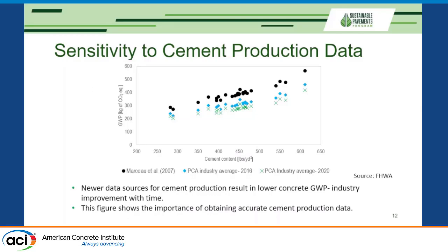I have shown you strong linear correlation between cement content and GWP. And it is true because cement is the most significant component. It has the highest contribution to footprint of concrete. But there is one more thing happening here. My LCA is following that prescribed in EPD program, so we are using only one inventory for cement. We are using industry average cement from 2020, which is the green axis here. And it doesn't give us bigger granularity to say, hey, cement from this producer or that producer. We are all just using one value for cement over the United States. And that is not ideal.